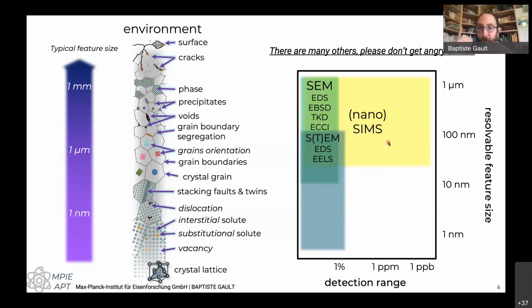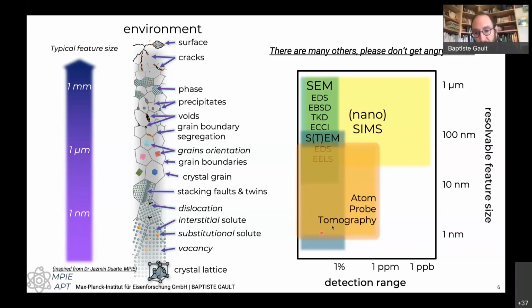And then there's also techniques like SIMS, so secondary ion mass spectrometry, where we have a primary beam of ions that is going to sputter the surface, and then we do mass spectrometry based on this. And there's a space here, somewhere down there, where we want to look at small features, and with a range of sensitivity, chemical sensitivity, roughly in the parts per million type range. And that's where the atom probe is sitting, basically.